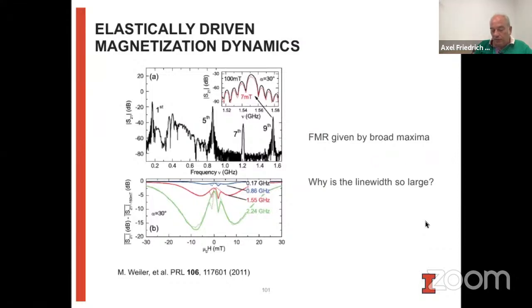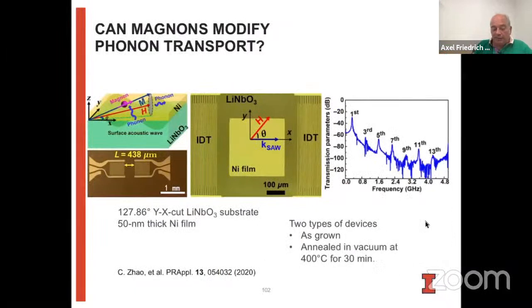And here you see an example where the FMR is given by these broad transition peaks. One of the things that we thought when we looked at it was, why is the line width so large? Part of it is nickel, which doesn't have the best damping to begin with. But maybe there are other reasons that are interesting. And so we started making our own devices. So we put nickel on lithium niobate. Here you see an image.